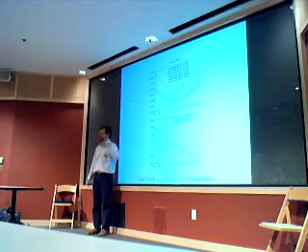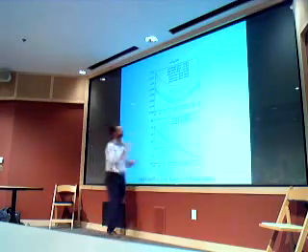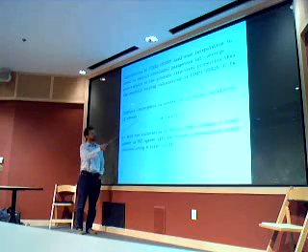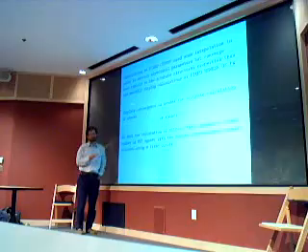the two curves, the thin and the thick: one is continuous, corresponding to a fixed number of plane waves, and one is irregular, corresponding to constant cutoff. These two lines tend to become much closer, and at 32 you cannot distinguish them. Okay, and in this sense, you need a complete convergence in order to have accurate calculation of stress.